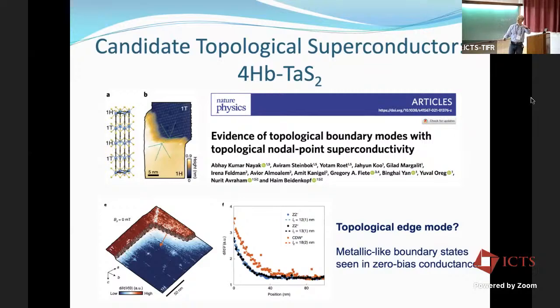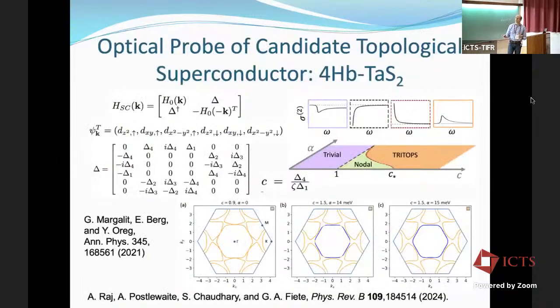And as you go from a 1H to a 1T step, you see that there appears in the spectroscopy to be an edge mode, which is gapless. So it looks kind of like a boundary mode. If there's topological superconductivity involved, you might think, oh, this is a Majorana mode along the boundary, because it decays into the bulk with the length scale that's set by the coherence length of the superconductor. So an important question here is, is this a topological mode? It looks like it in STM.